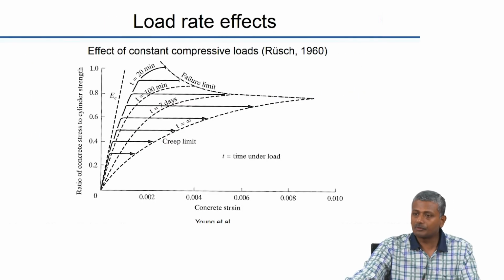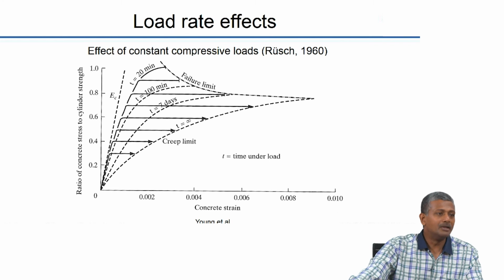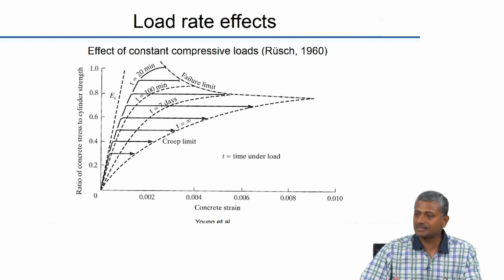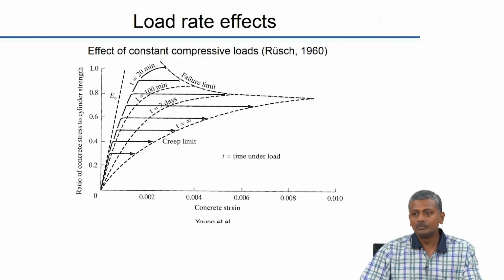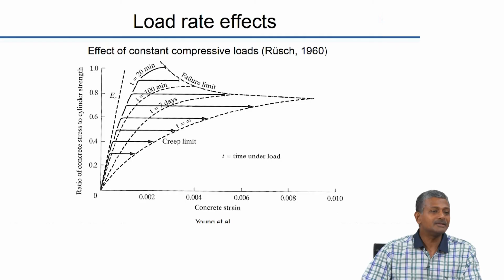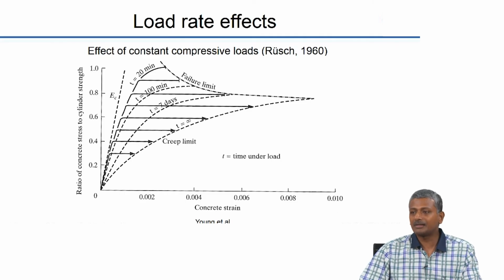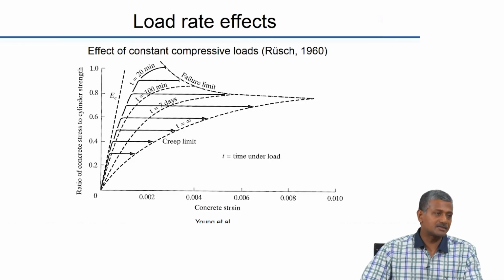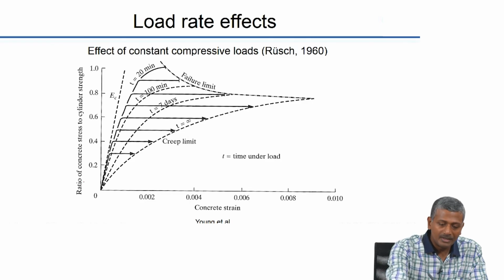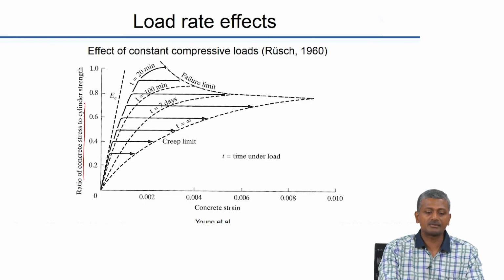But of course, this is something that you have observed in the lab. When you test concrete very fast, that means if your loading rate is very high, you get higher strengths. The higher the loading rate, the higher the strength of the concrete. The lesser the loading rate, the time dependent deformation effects also start playing a role in increasing the extent of strain. So, what is shown here is the ratio of concrete stress to the cylinder strength.